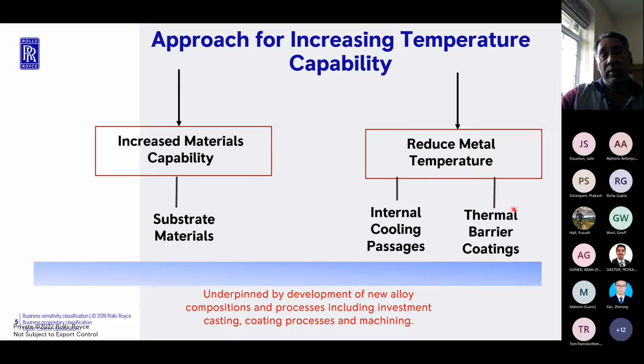Another, equally effective way is if you deposit a ceramic on the surface of the blade. So effectively, you put a layer on the blade, like a coating or a thermal barrier coating, which has a very low thermal conductivity. So if you remember, what I said was one of the groups in materials actually looks at thermal barrier coatings, or the surface engineering group. So roughly, you've got two methods by which you can develop materials. One of them is, for a given material, you can either go down the coating route, or you can have more intricate methods of cooling, which again is linked to the manufacturing process. And the other aspect is, well, you just end up developing an alloy which is stronger, or which is higher melting. So that's the very broad brush way in which you can develop alloys for increasing the temperature capability.